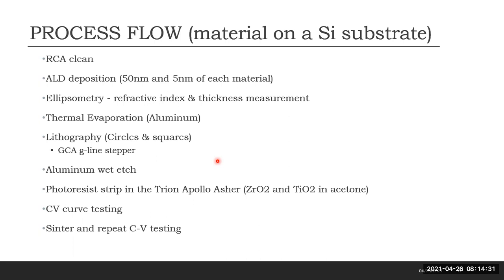For the alumina wafers, the photoresist was stripped in the asher. However, our results indicated more plasma damage than expected, so the titania and zirconia wafers were stripped in acetone. CV testing was done then. The wafers were sintered in forming gas at 450 degrees Celsius for 30 minutes, and the CV testing was done again.